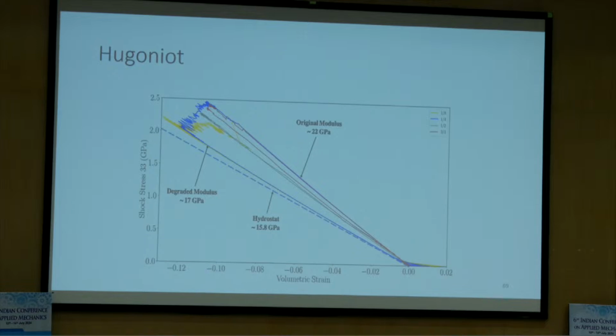Okay, this is the Hugoniot. If you are a shock physicist, you will understand. But initially what happened, this is the shock stress versus volumetric strain. You begin at 0 and you compress the material along this line. That's the original modulus, okay? See, it goes up. And then damage initiates, and you unload at that point, you come back here to 0. So eventually what happened, if damage occurred, the degraded modulus went from 22 to 17, okay? And then it is coming towards the hydrostat.